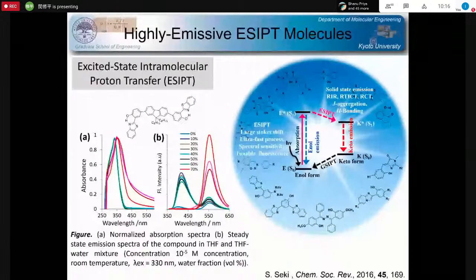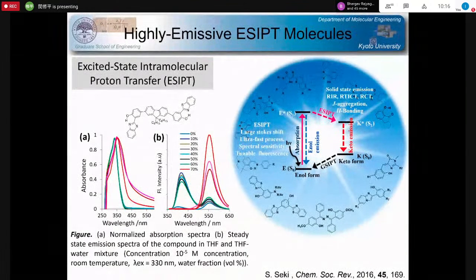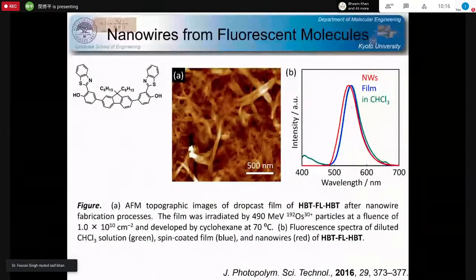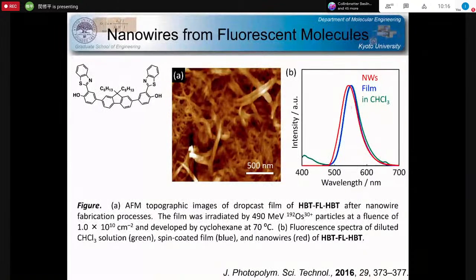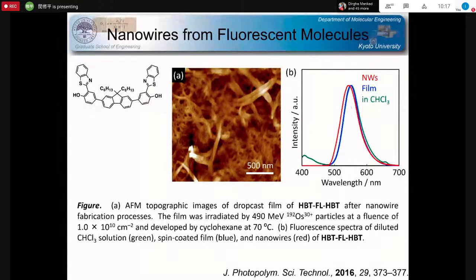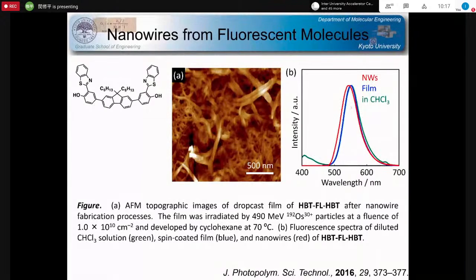We go to another topic here, and so the photofunctional materials are also applicable for the sensing of some other chemicals. And this is a case of the nanowires fabricated for the highly emissive molecular systems, where, as seen in the chemical structure of the molecules, on the right-hand side and left-hand side, the same molecular subunit was embedded into the one single molecule. This molecular subunit is often called the ESIPT active molecular system. And even in the solid state, this type of molecules exhibit extremely high fluorescence quantum efficiency, reaching up to 0.8 or 0.9. And in this case, we could realize the highly emissive one-dimensional nanowire.